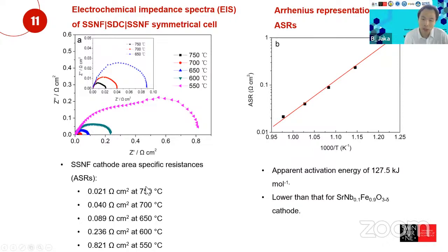Okay, so what we can conclude, or what we can say in here, is that the ASR for this particular cell is 0.021 at 750 and up to 0.821 at 550 degrees Celsius. The other thing that is interesting is the activation energy. So the apparent activation energy that we have for this particular cathode will be 127.5 kilojoule per mole, which is much lower than the S and F cathode.